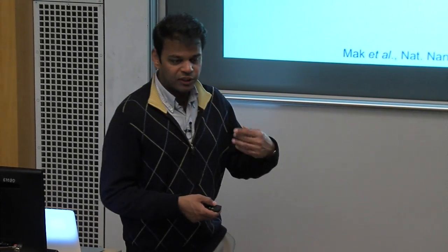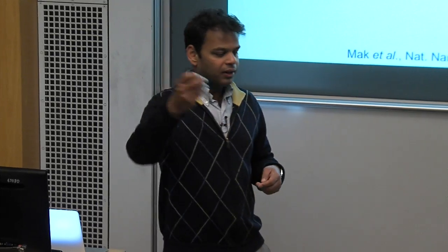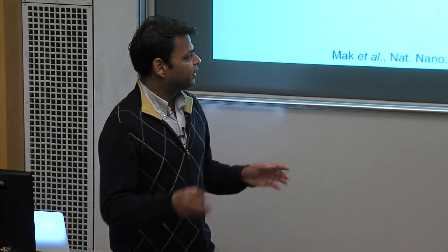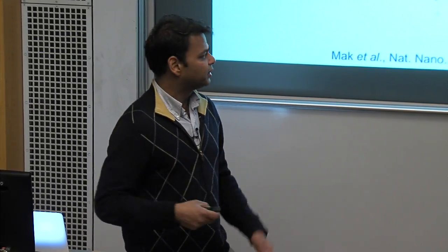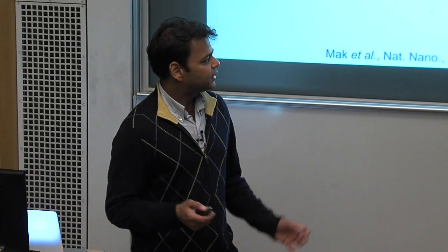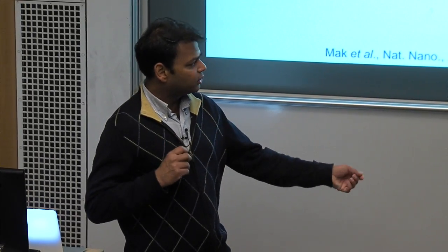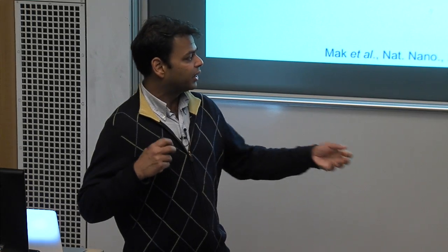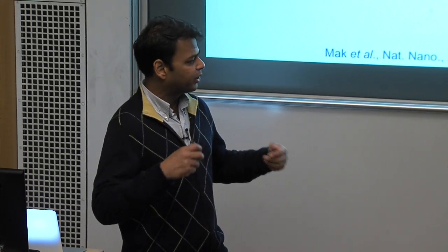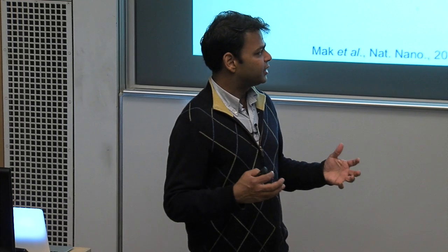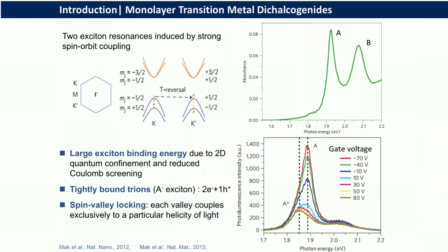Because the screening is very weak in these materials, electric field lines can escape the material and then re-enter. Because of that, the electron-electron interaction length scale, or exciton-exciton or exciton-electron interaction length scale, of any excitations that you create in the system becomes much longer range than in conventional semiconductors, because there's very little screening.